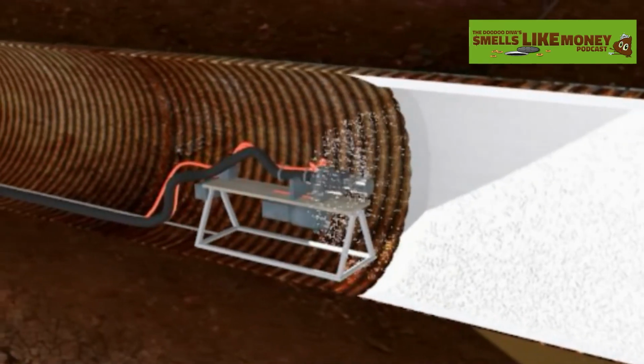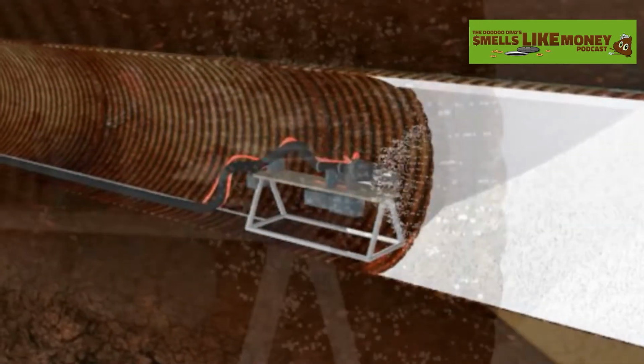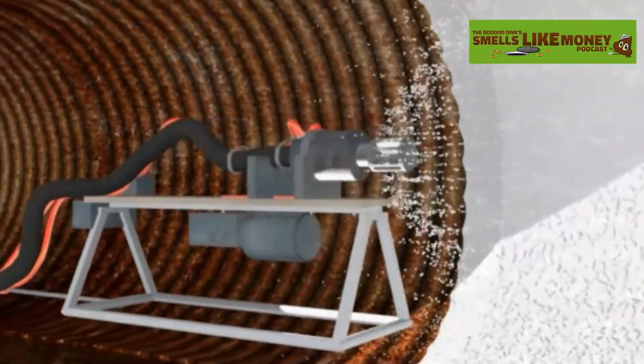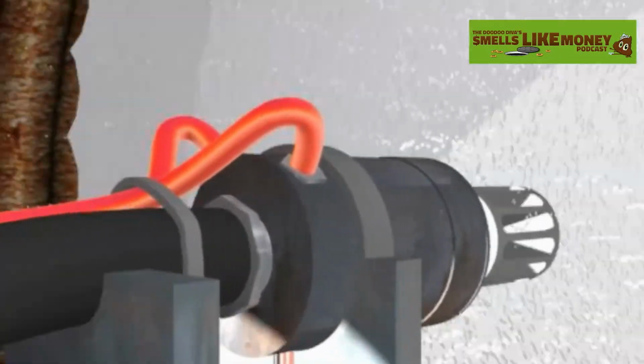Okay. The difference between that and what you're going to call your traditional plastics is we're going to prefer to be wet to get a good bond, where they're going to prefer and in most times require that the concrete that they're going to be applied to has been sitting for 28 days or so to be cured if there's a build back coat. And they're going to require that that concrete be pretty much bone dry in order to get a good bond. And so you can pressure wash and we can go right over that and be wet. And then the reality is, if you want to apply an epoxy or a polyurethane to our material on top of that, you could do that much quicker than you could do it with a normal cement, because we're going to build about 70 to 80% of our strength in the first couple days. So where you might have to take a treatment tank down for a month to do a rehabilitation on it, you might be able to do that same thing in a week.